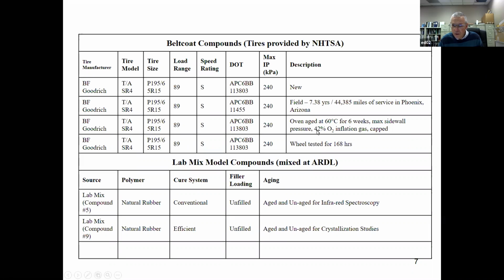Maximum sidewall pressure, 42% oxygen inflation gas. And then there's a wheel tested tire, 7 days on the road wheel. And this is lab mixed compound, natural rubber, conventional cure, and natural rubber efficient cure, unfilled, aged and unaged for FTIR and for crystallization kinetics.